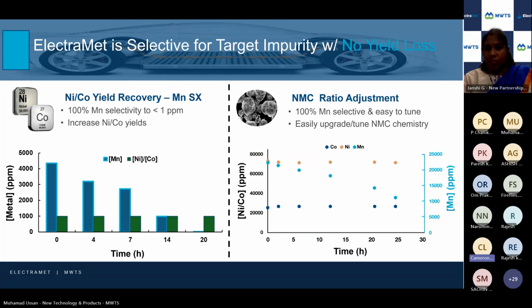And then looking at the right side, so this is when the customer who wants to make the cathode active material, but the ratio of nickel to manganese to cobalt isn't conducive to make the high value battery material. So they need to remove part of the nickel to have it sort of match with the cobalt, so we can make this high nickel, low manganese cobalt solution. So our solution is able to very selectively tune the manganese concentration in that NMC leach shape, so that once the ratio is set, they can make their cathode active material and have their valuable product. Next slide, please.